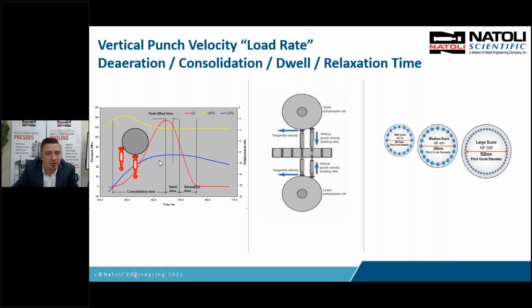So if you look at this graph here, this is an example, one compression event. As the punches hit the rolls, the punches are coming together and consolidating. That's what all of this time is right here. And again, that's a function of the roll diameter. And then after you reach its consolidation, you get into the dwell time. And this program is using peak to 20% on the unloading. Some programs use 10% to 10%, but the time's still the same. It's a function of the head flat and the turret tangential velocity. Then you have the relaxation time right here. This is the whole compression event. So dwell time is just a small area right here. Consolidation is a huge part of this compaction event. So the compression roll diameter and the turret velocity play a role on the consolidation time. This is very important to us to understand.